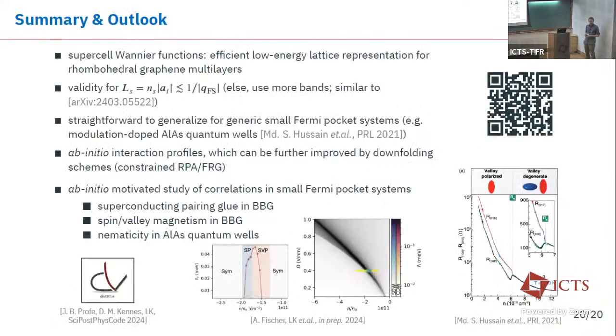And with this, I would like to conclude my talk and summarize really quick what we achieved in this work. We wrote down supercell Wannier functions for a very efficient low-energy lattice representation for rhombohedral graphene multilayers. Those are valid as long as the size of the supercell does not exceed the size given by the Fermi pocket. So the inverse of the Fermi pocket diameter must not be on the same order as the size of the supercell. Otherwise, you need to take more bands into account. There's a work that doesn't do Wannier projection, but does something very similar. They write down a minimal model for the case where the supercell size is actually larger than the size given by the Fermi surface diameter.